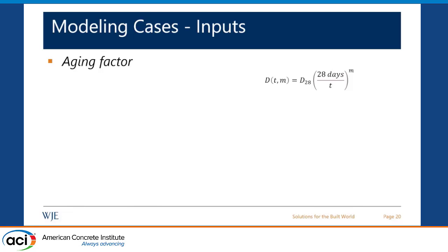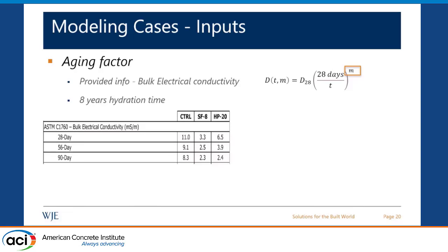Then talking about aging factor. The diffusion coefficient decreases with time as concrete matures, and we describe that in our model based on the aging factor. So here, the information that was given as part of the inputs was mainly bulk electrical conductivity testing. And I'm showing here the results we have from that test. It was also given to consider 8 years of hydration time. However,